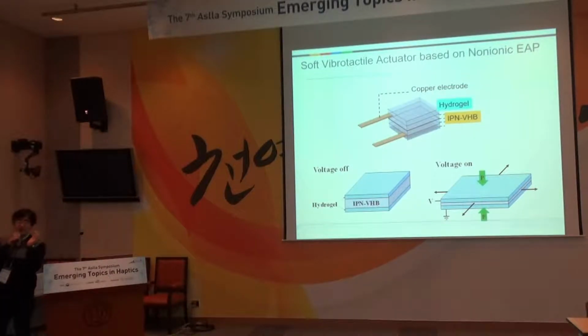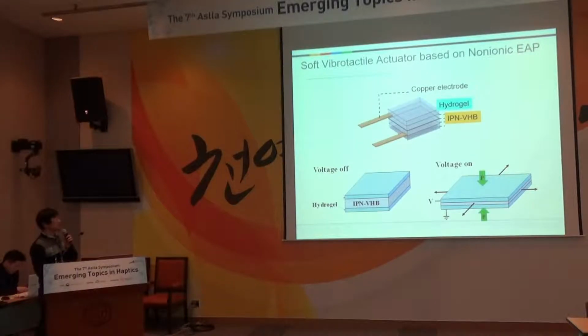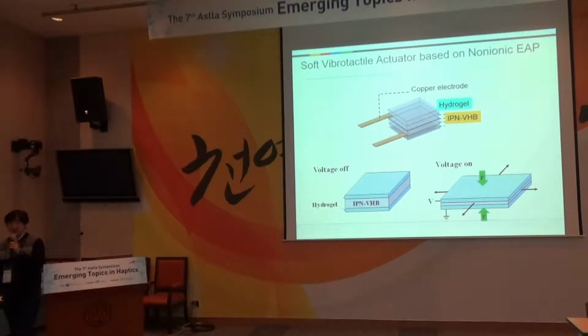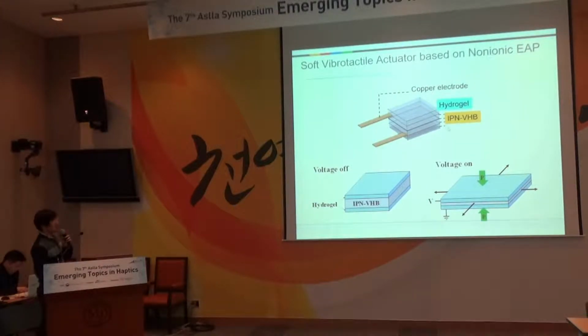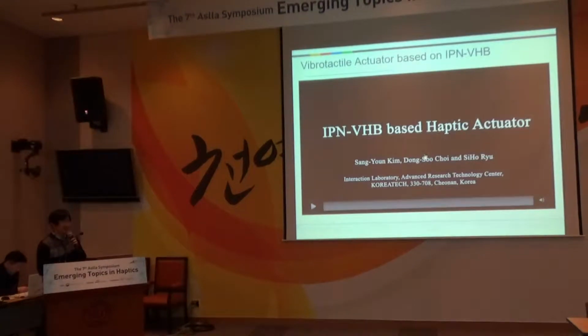As I said before, the weak point is that it needs a stretchable electrode. So we considered how we can make a stretchable electrode. We studied that, and hydrogel had the best performance. So we made the hydrogel, and applied it on both surfaces of the VHB, and then we provide voltage. We can create vibration with this kind of haptic actuator.